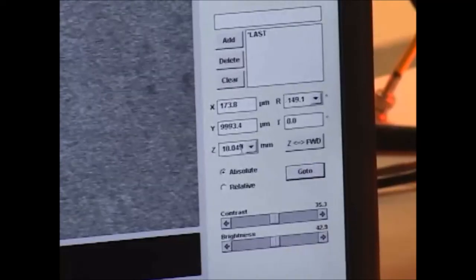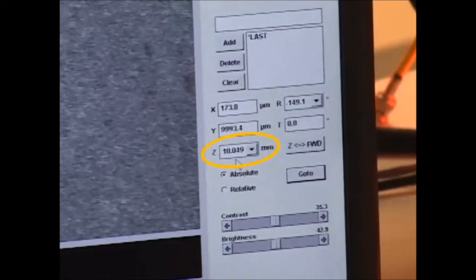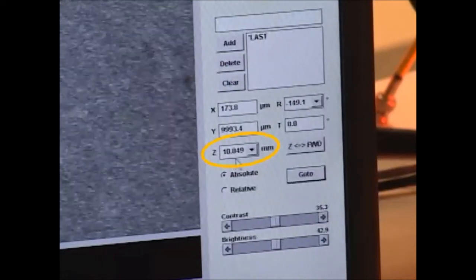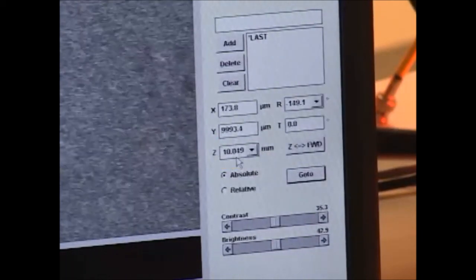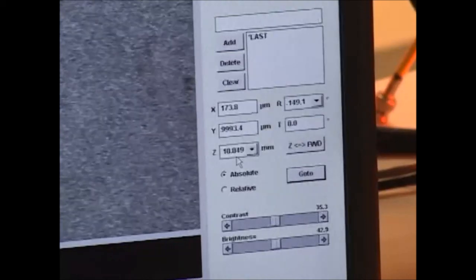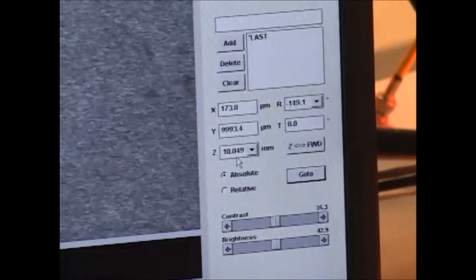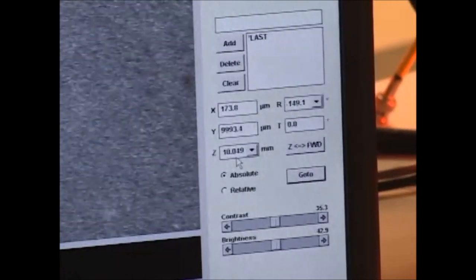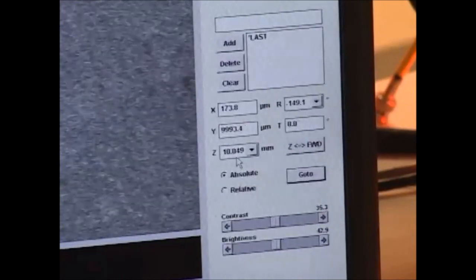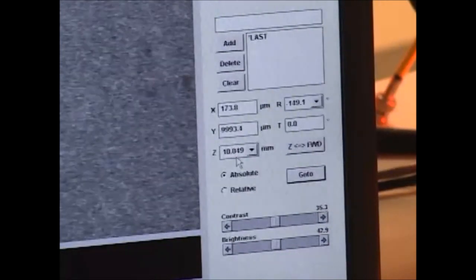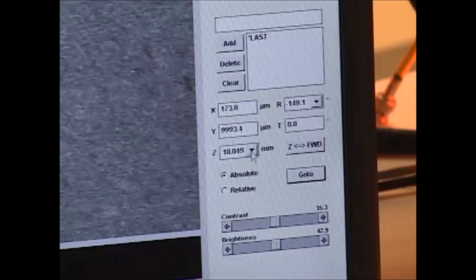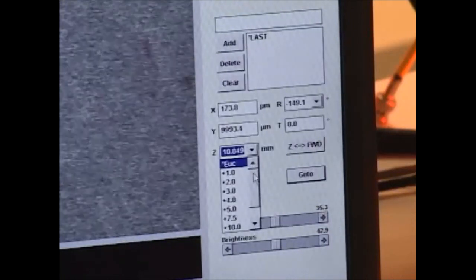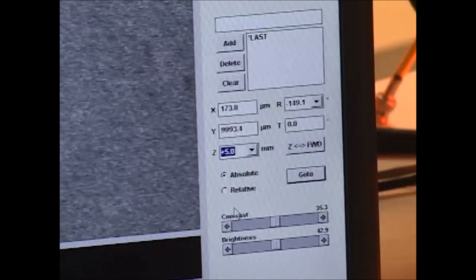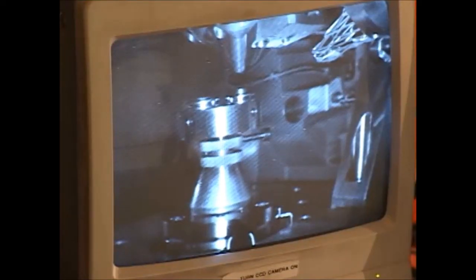And you see that it's updated the Z height with 10.049 millimeters. So I was off in my initial movement by 0.049 millimeters, which isn't much under normal circumstances, but it makes quite a difference in the focal length when we're actually trying to look at a sample. So I'm at 10.049. I'm going to drop this stage clearance now down to 5, and I will initiate that movement, and I'm ready to cancel in case the cancel box opens.